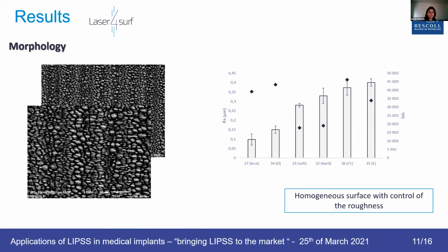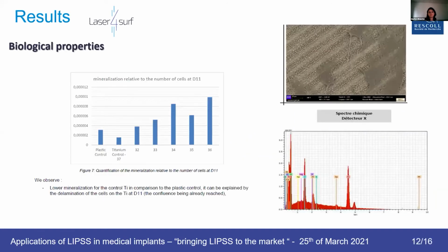If we look at the morphology, we see here nanotopography. We can see very clear and nice LIPSS formed on the titanium surface. And to come back to what I've just said, we can really play on the surface roughness. This is the raw titanium with a roughness factor of 0.1, and we can jump up to 0.4 thanks to the laser surface treatment. So we have very good control of the roughness, and we can play on it according to what we need, and we can improve the surface state thanks to Laser4Surf. And we wanted to compare it with biological property, which is a key feature for osteointegration.